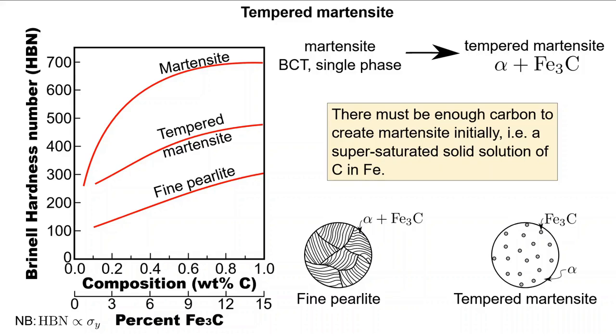Using hardness testing, the properties of martensite, tempered martensite, and fine pearlite can be compared. By fine pearlite, I mean the pearlite one would attain for a eutectoid composition. The hardness value — i.e., the Brinell hardness number — is roughly proportional to the yield strength. For very low amounts of carbon, the net hardness is relatively low for all three types. As carbon increases, so too does the strength. However, in order to attain this type of response, there needs to be enough carbon in the material — approximately greater than 0.28% carbon — to force the original martensite to form and therefore also drive the tempering process to form cementite.